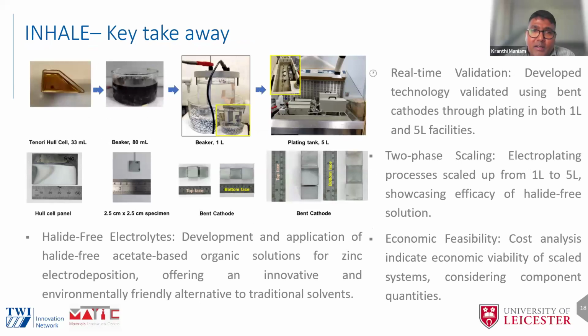So in short, this is the snapshot of the work which I've done as a part of my Marie Curie. I started with a 33 ml Hull cell to optimize the current densities. I could do a 2.5 centimeter by 2.5 centimeter specimen using an 80 ml solution. Then I transformed it to a 1 liter scale, where I used not a flat part, but a complex geometry like a bent cathode to understand its coverage, and I could still get that. And finally, I could set up a line and run a throughput there, and you could see that you can get a good coverage.